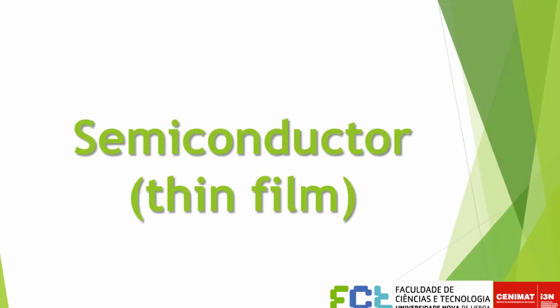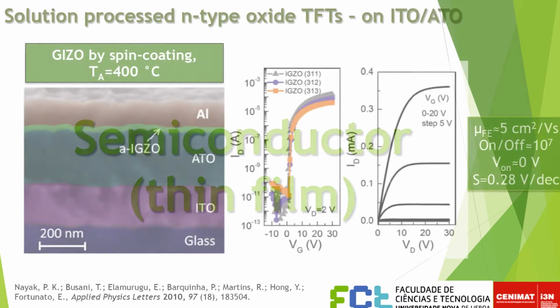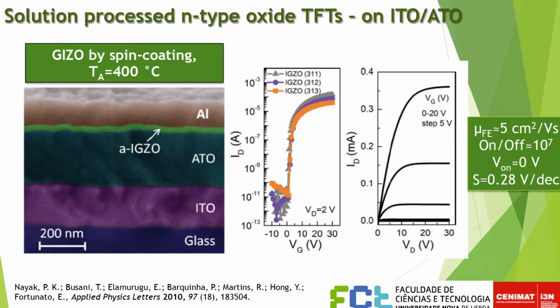Also, now I will present you some results. I will start with the semiconductor, but only on solution process, because the sputtering was already done. For example, here are some previous results on solution process. We tried to mimic what we have done using a physical approach, the sputtering technology. So we start with GIZO by spin coating. The final temperature was 400 degrees, but we achieved a mobility of 5 square centimeter per volt per second. Of course, the temperature was still a little bit high.